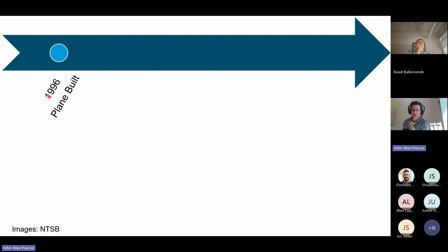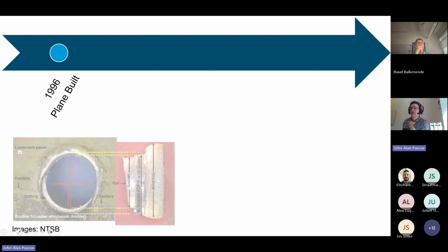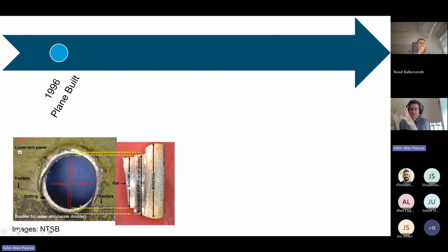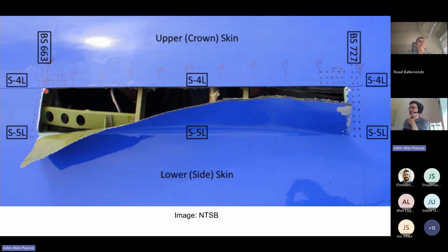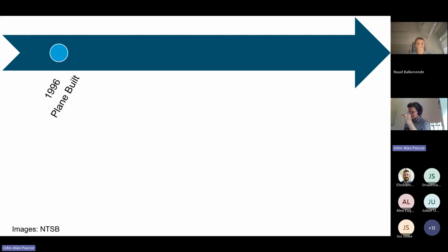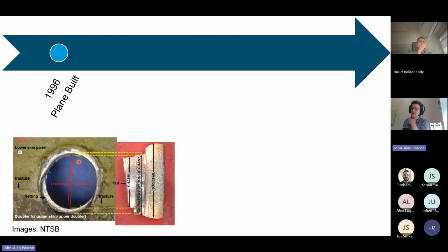So the plane was built in 1996. But during the manufacturing, something went wrong. Some of the rivets were installed incorrectly. So as you saw, this failure is along this rivet line, right? And some of these rivets were installed at an angle, which means that this hole, if you look, it should be a circle, but you can see that's actually an oval. Because of that hole being the wrong shape, there was a bit of play in the joints, so these parts could rub past each other.